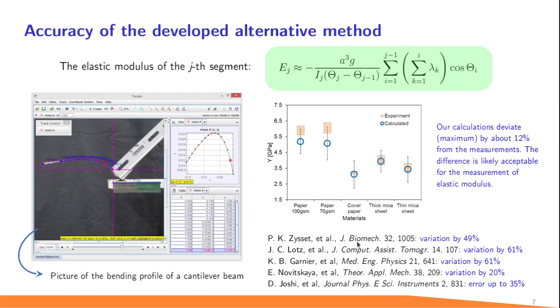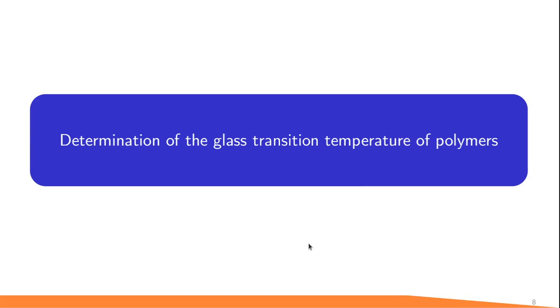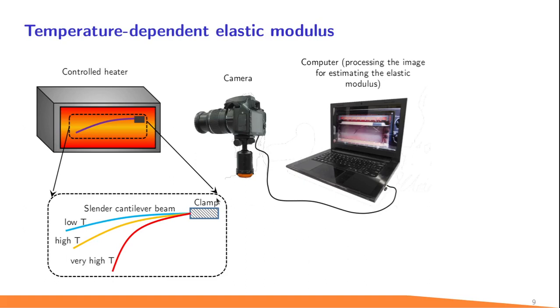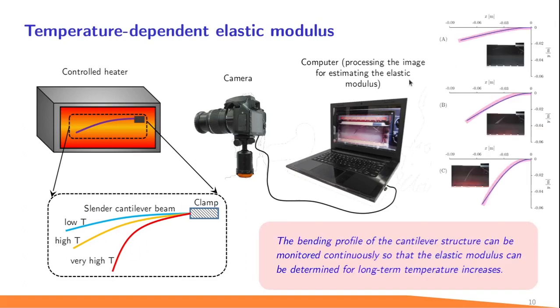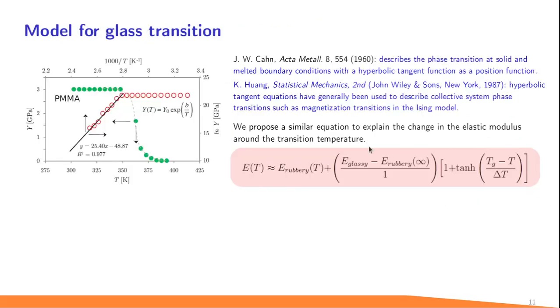And we also estimate the effect of temperature on the elastic modulus. Since the bending profile of the sample was recorded continuously during temperature rise, the proposed method allows continuous monitoring of the material modulus with temperature. And here, in this picture, the closed circles represent the calculated elastic modulus of PMMA at different temperatures. We observe that the elastic modulus is nearly unchanged at around 3 GPa when the ambient temperature was increased up